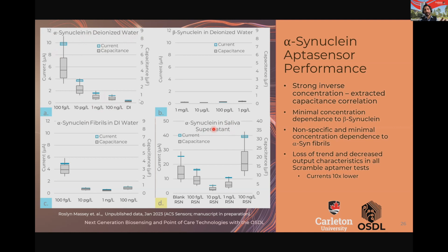Now, since the aptamer is designed to be specific to alpha-syn monomer, we have also demonstrated that it doesn't interact with even similar synuclein proteins, which are not alpha type. So it's very selective to binding to alpha-syn monomer, which is great because it allows us to look at the total picture and say how much of the alpha-synuclein monomer has oligomerized or has become fibrils. So this is great because it shows strong inverse concentration to presence of alpha-syn monomer, and it also allows us to create correlation plots for total to oligomeric concentration of alpha-synuclein, which is a very important parameter that can be monitored for detecting Parkinson's.